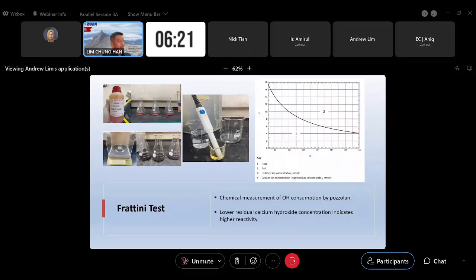Finally, this is the third and final method that I'm going to use, which is what I call the chemical method, the Frattini test. If you can remember when I was going through the pozzolanic reactivity slides just now, SBA or pozzolans require the presence of calcium hydroxide to react with, to produce this CSH paste. So what this test does is we artificially introduce calcium hydroxide. We chemically produce some calcium hydroxide, and then we drop our pozzolanic material in there, mix it in to see whether this calcium hydroxide gets consumed or not.